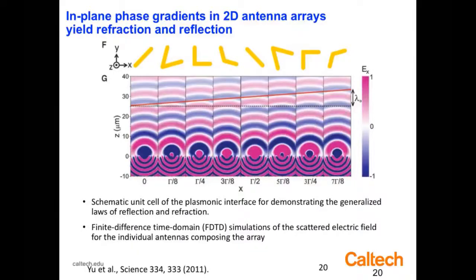This is from the paper by Nanfeng Yu and Federico Capasso, who first showed plasmonic antennas of this kind scattering light from a surface with these different kinds of antennas. These antennas have about the same scattering amplitude, but they have different phases. You can see a couple of wavelengths away from the surface, this Huygens principle is beautifully at work, that the scattered spherical waves coming out of these antennas are merging together into a plane wave phase front that's refracted. And it's refracted due to the phase difference between these antennas. Okay, and this has led to a huge explosion.